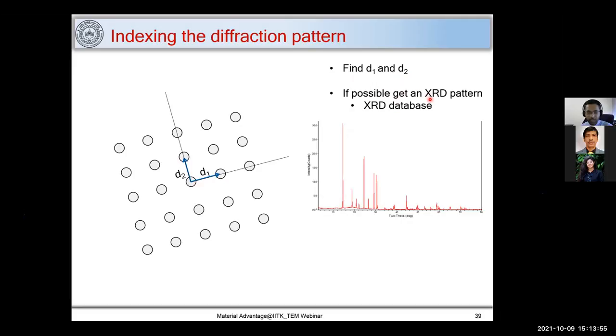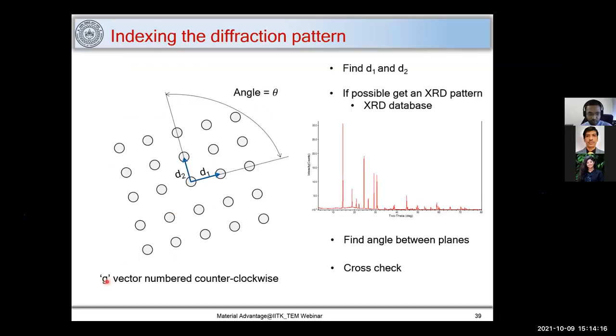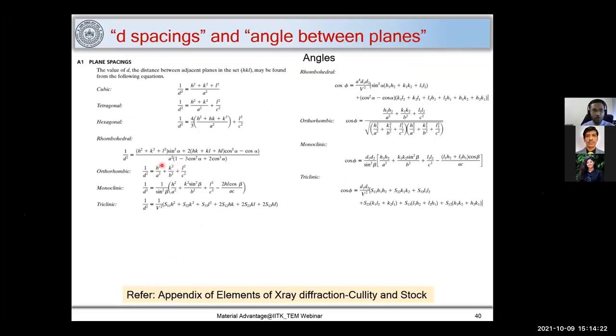Then try to find an XRD pattern, or you may have an XRD database, and find the closest match with this D1 and D2. Once you do that, find the angle theta between these two reciprocal points, and then cross check. How will you do the cross check? Here the G vector will be marked in a counterclockwise way. To cross check, you have these formulas, which are given in the appendix of Elements of X-ray Diffraction by Cullity and Stock. So you have different d-spacings and you have cos phi values. For different crystal structures, they are mentioned already.